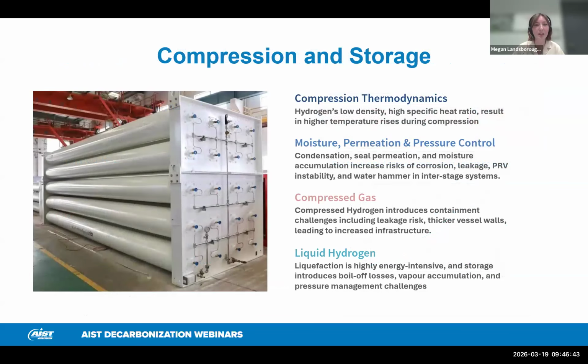Okay, if we want to take a look at compression and storage, my first 2 points here are focusing on compression, and then the bottom, I will focus on storage. So first with our compression thermodynamics, hydrogen's low density and high specific heat ratio result in higher temperature rises during compression, increasing compressor discharge temperatures and thermal stresses. With your moisture and pressure control, condensation, seal permeation, and moisture accumulation increase the risks of corrosion, leakage, PRV instability, and water hammer in interstage systems.